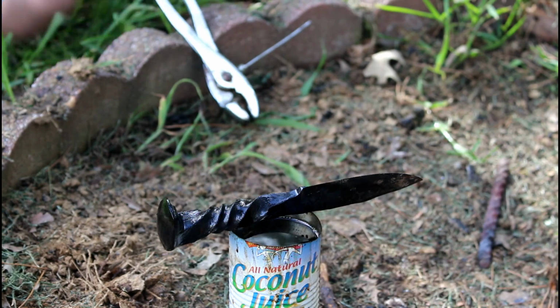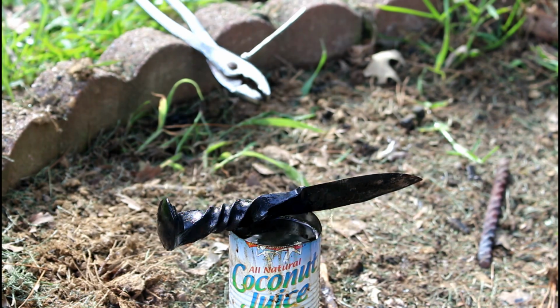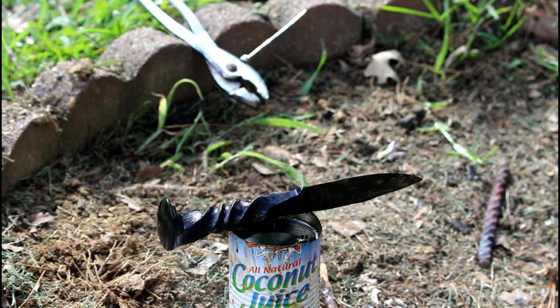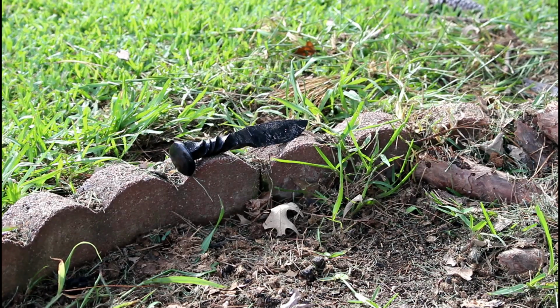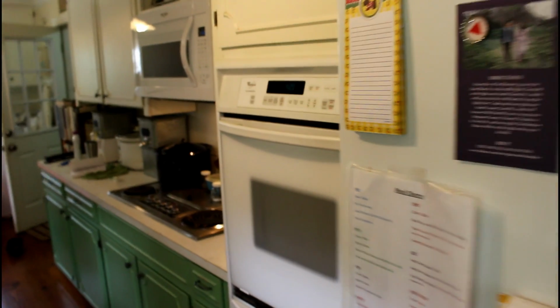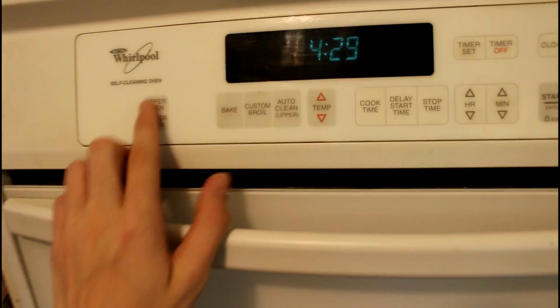After quenching, the steel is extremely hard. So hard that it is about as brittle as glass. If you were to drop it or subject it to any amount of force at this point, it would be liable to shatter or crack. The next step is to heat the blade up again, this time to 400 degrees Fahrenheit. This relieves the stress built up in the steel and softens it down a bit, and you end up with the perfect hardness for a knife blade.